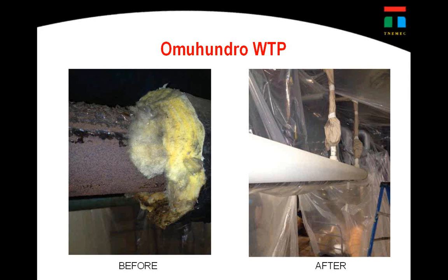So if we can stop the CUI from ever forming, the water from forming underneath, in this particular case they were just doing this to eliminate the sweating on these pipes. So now they've taken off all the insulation. They're now putting Aerolon on the whole plant inside this application, and that's where it's being utilized. If you wanted to add more insulation on top of this because you wanted to achieve a very specific R value, the Aerolon can give you up to 1 or 2 if you wanted it to, and then you could add more to it. Personally, I think that we were seeing more people interested in applying this as a CUI prevention issue and then adding insulation if they needed more. Thank you.